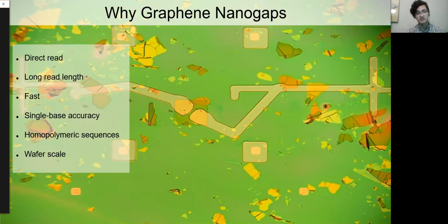Now let's talk about the devices themselves. On the picture right behind you, you see the silicon nitride wafer. On the silicon nitride wafer, there is a membrane. In the membrane itself, there is a micropore. The micropore is situated right in the middle and is going to be the tunnel for which the graphene is going to traverse, and this is where we ideally would like to put our graphene, and we will make our break in the graphene, aka the nanogap, over it.